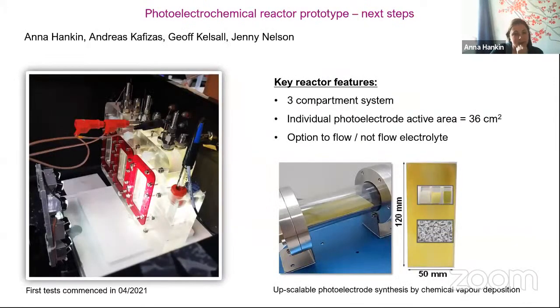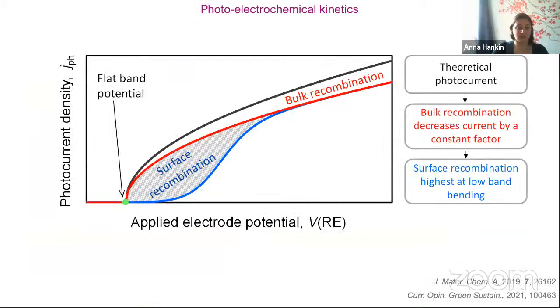So one final thing I wanted to say is that, yes, I focus on engineering, but I mentioned that I develop microkinetic models to try and help with the engineering, and I want to just mention an example of the kind of thing I do. If you were to take a photoanode material such as hematite or bismuth vanadate, and characterize it using standard electrochemical techniques, so for example you apply an electrode potential and you measure the photocurrent, you get a profile that looks something like the blue line. What's predicted theoretically is the black line, and this is the Gärtner-Butler model that I referred to before.